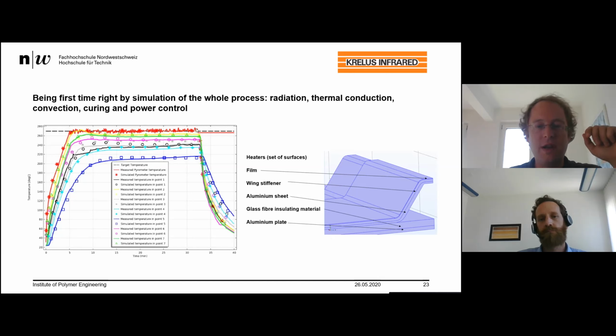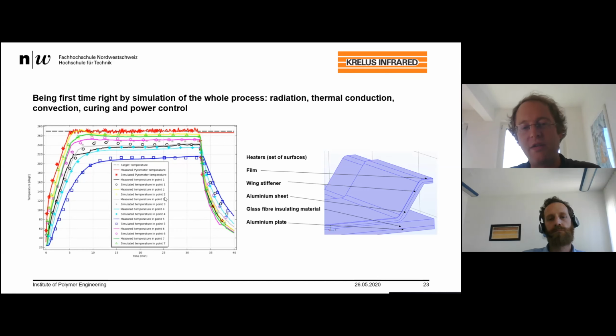And if you look at the curves, the three upper curves are the gradient in the vacuum setup, because we are applying a two-foil setup to maintain the vacuum, and there's a breather which is blocking the temperatures a little bit. And then we have the gray, black, and blue curves, which are the temperature in the part itself. So the gradient in the part is low, and then the blue curve represents the temperature below the insulation material. So we have a kind of gradient of the temperature through the thickness, and the trick is, with the simulation, to modify it in such a way that in the composite part we have a homogenized temperature without exothermal overshoot in the beginning.